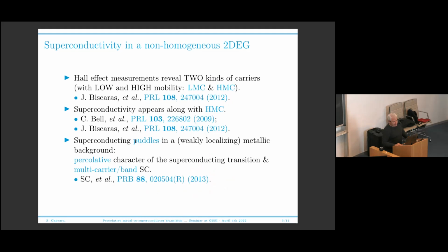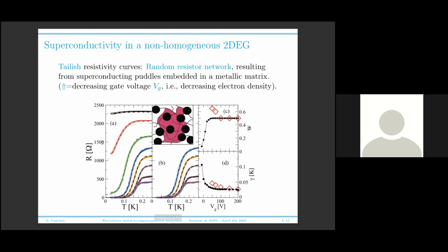Our description of the system is like this. We imagine that we have superconducting puddles embedded in a weakly localizing metallic background. And I will try to convince you that this will give rise to a percolative character of the metal to superconductor transition, with possible resistance curves like this. So here the colored curves are the experimental data, and the dashed lines are our fitting with the effective medium theory. As you see, the data are rather satisfactorily described by the theory.